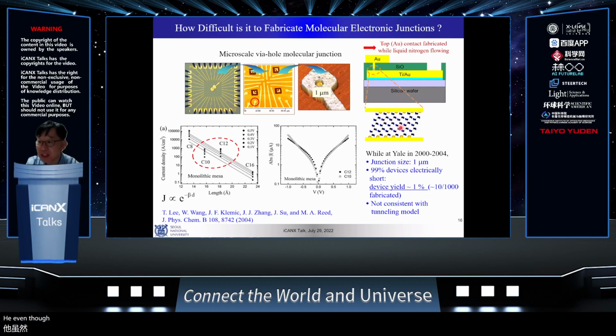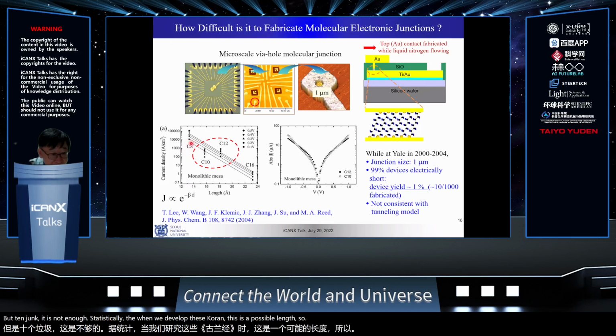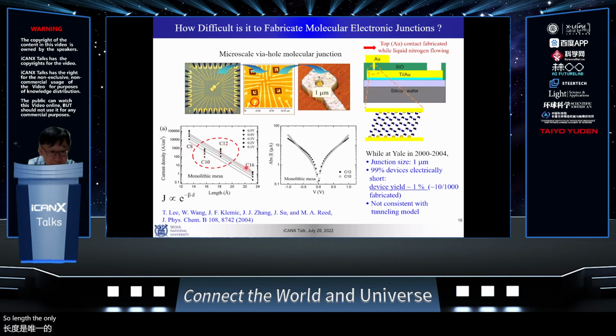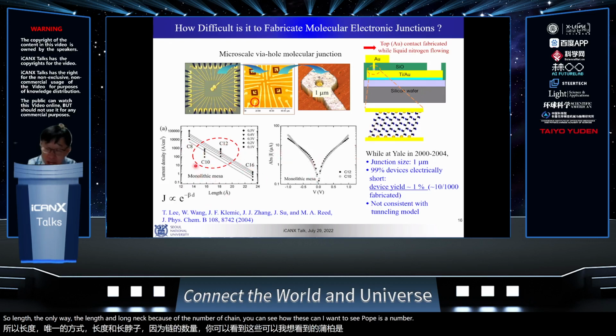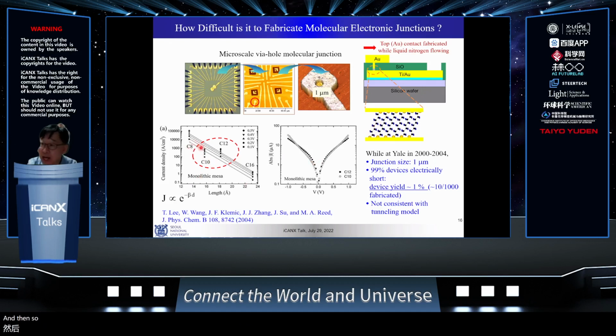Okay, even though this is a long process, when, for example, I fabricated 1,000 junctions, molecular devices, only about 10 devices were working. So all 990 devices were dead because of the electric short problem. The short just means an electric wire shorting problem. But 10 junctions is not enough statistically. So when we plot the current density as a function of length, this is the short length, middle length, and long length, according to the number of chains here. So you can count the chains 1, 2, 3, 4. This is the number of chains, and the length is D. I told you about the exponential dependence on D.